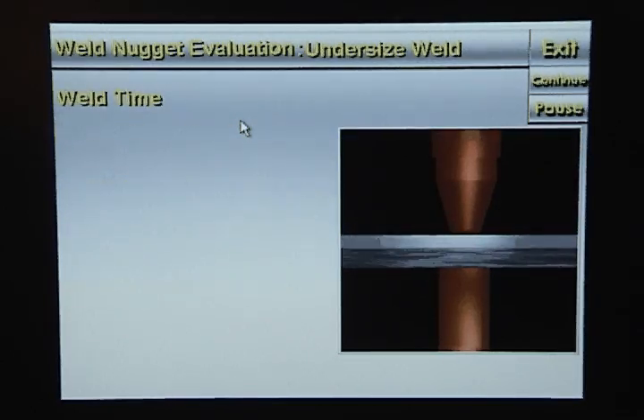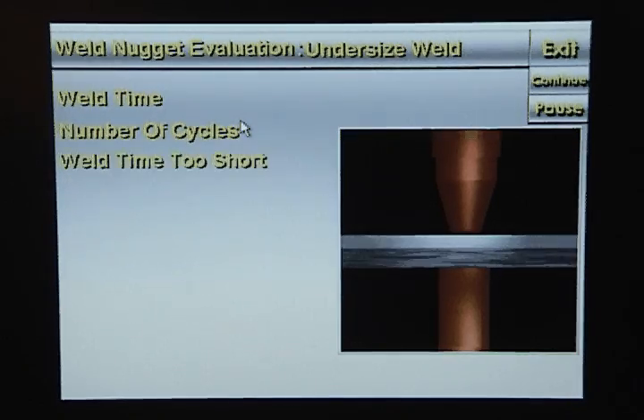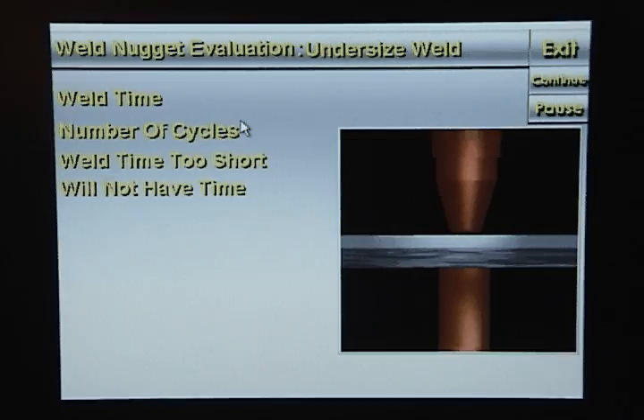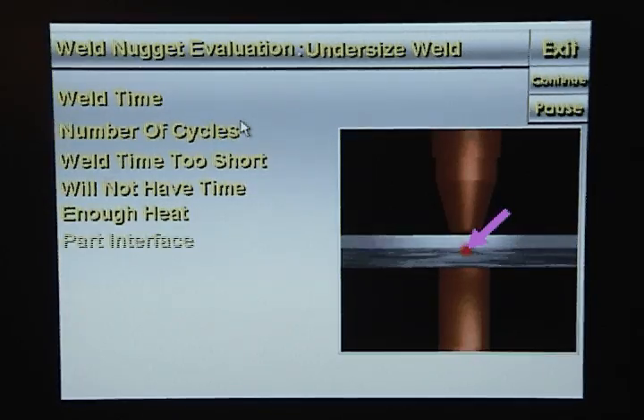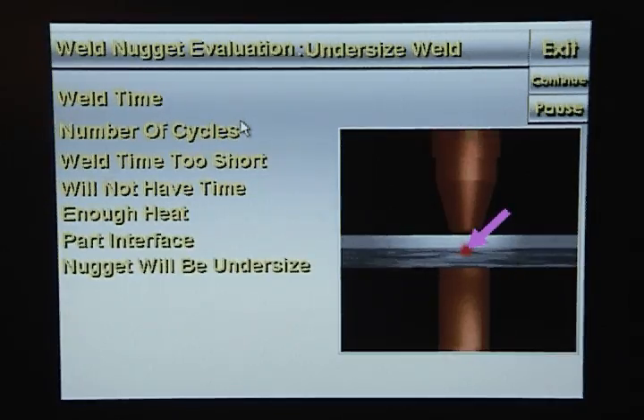Weld time is the number of cycles that weld current flows. If the weld time is too short, the weld current will not have the time to generate enough heat at the part interface to melt enough metal to form a good weld.